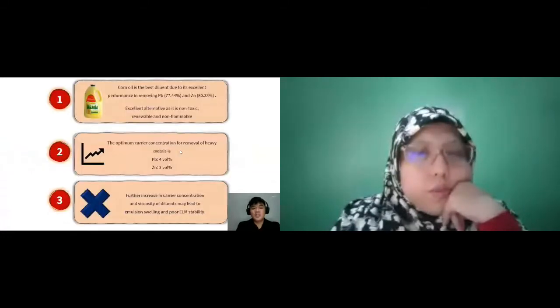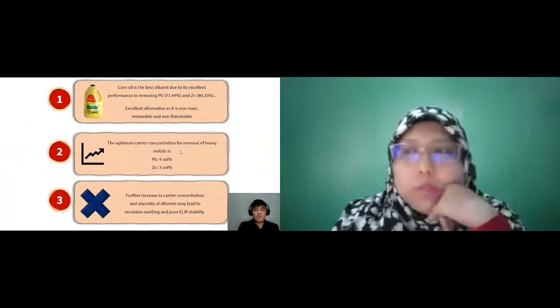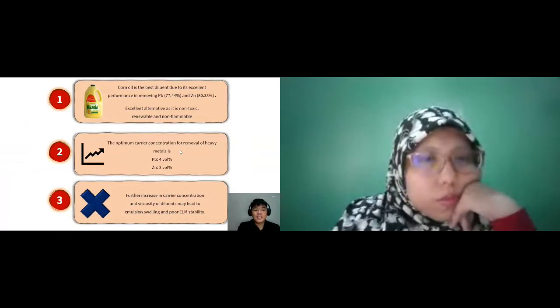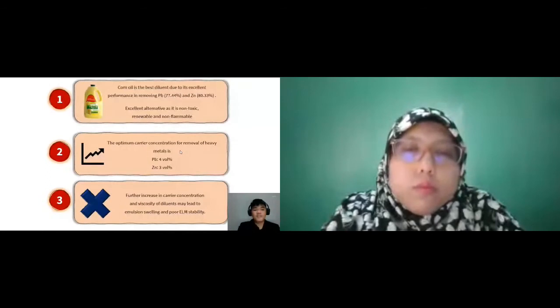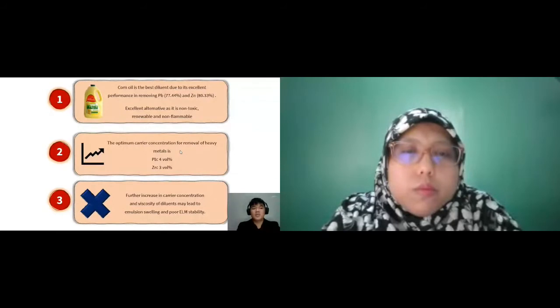As the conclusion, the study concludes that corn oil is the best diluent to be used in the emulsion liquid membrane due to its excellent performance in extracting lead and zinc. It also offers a greener alternative as it is non-toxic, renewable and non-flammable, which is very safe to be utilized in the emulsion liquid membrane process. The optimal carrier concentration for heavy metal removal is 4 volume percent for lead and 3 volume percent for zinc. The study also concluded that a further increase of carrier concentration beyond this value will result in emulsion swelling, poor emulsion stability, and inevitably low extraction efficiency.